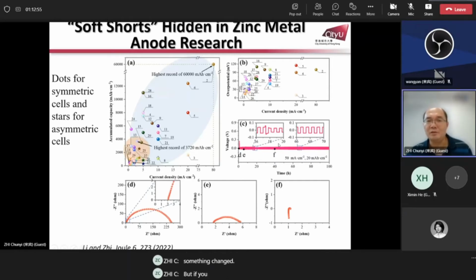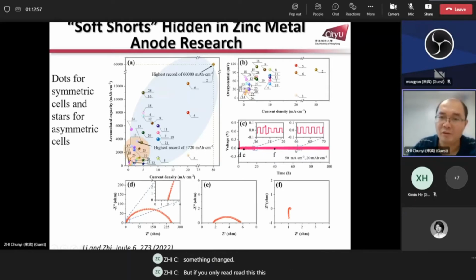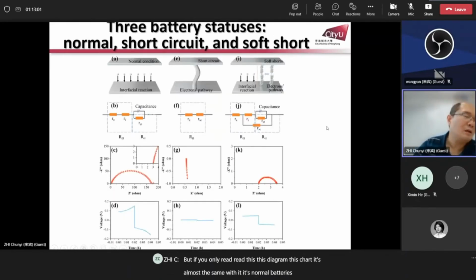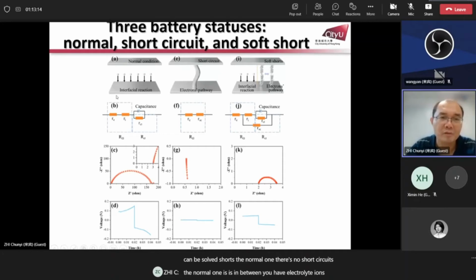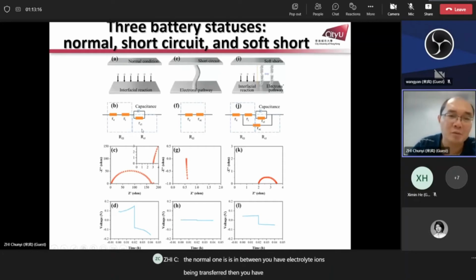But if you only read this diagram, this chart, it's almost the same as normal batteries. Then we analyze the battery status. That can be normal, short circuit, or soft shorts. The normal one has no short circuits. The normal one is in between. You have electrolyte, the ions being transferred. Then you have capacitance and resistance.